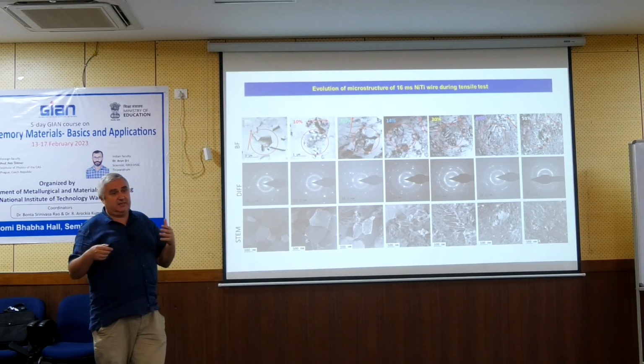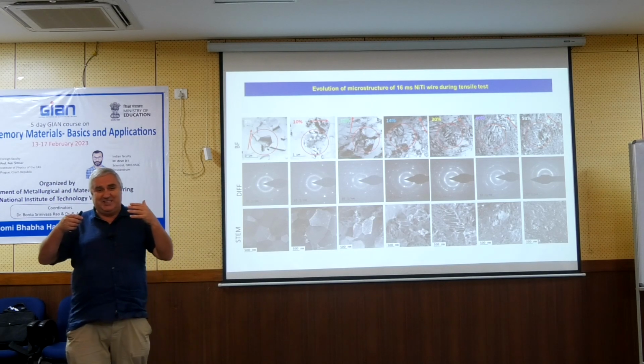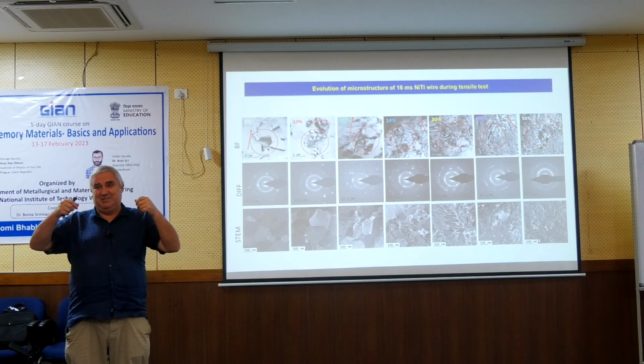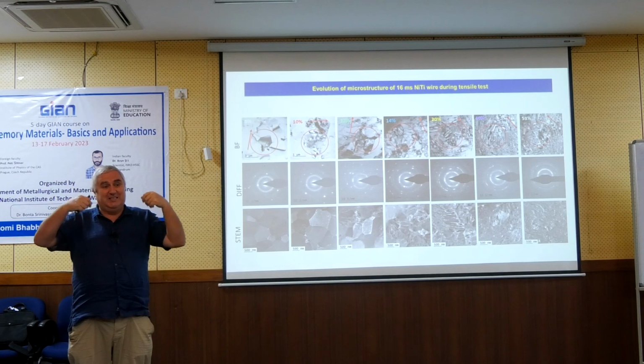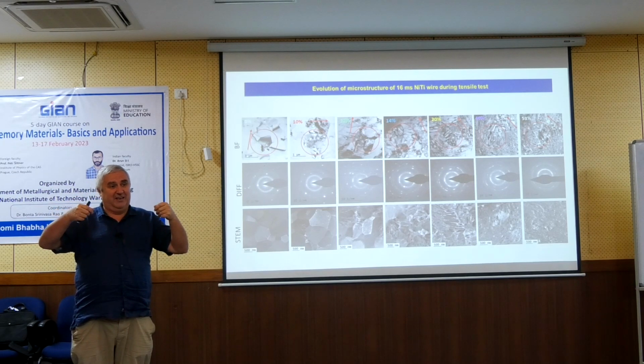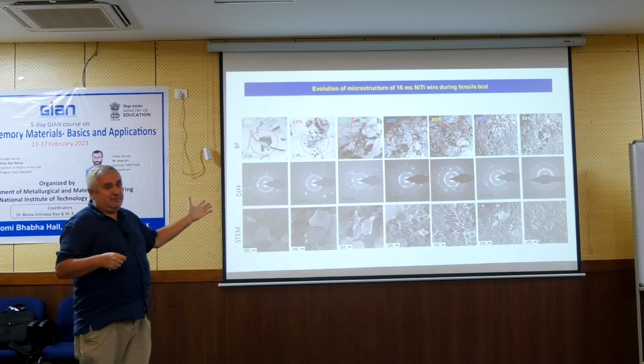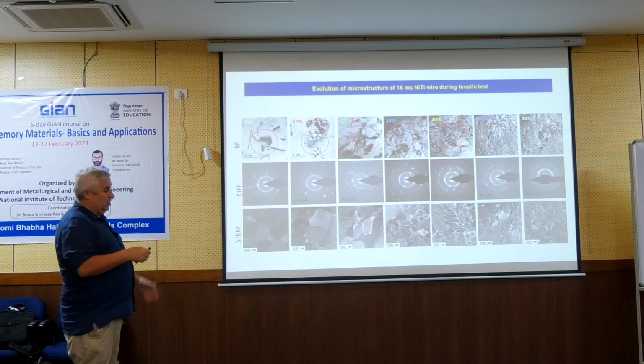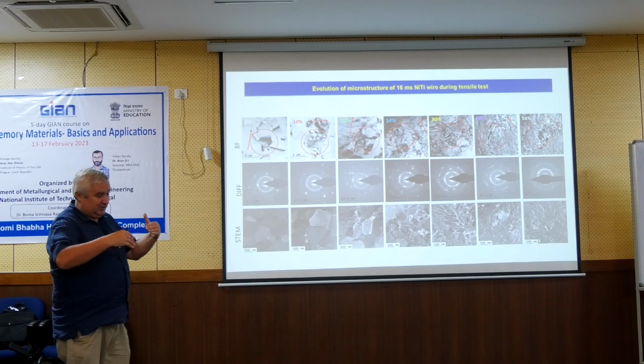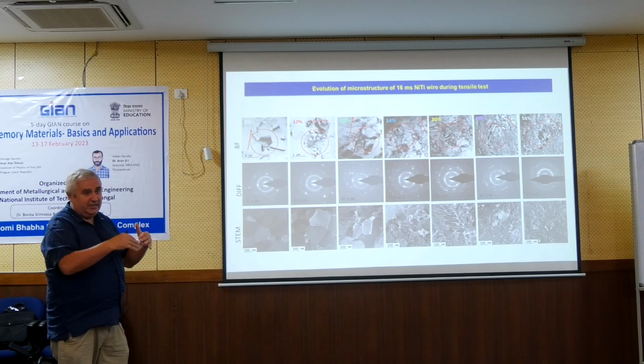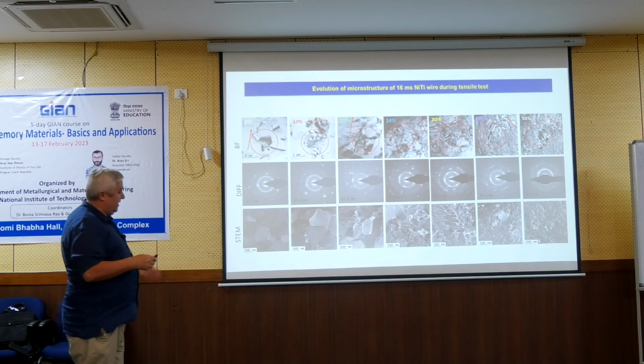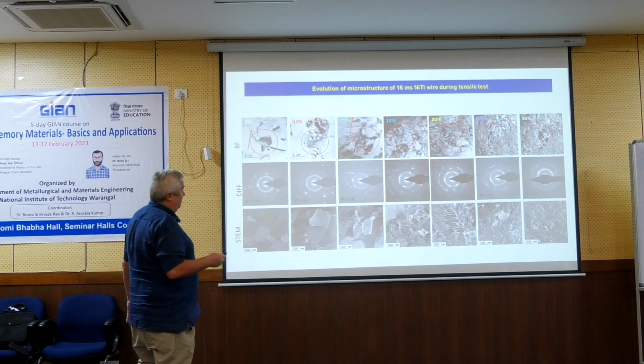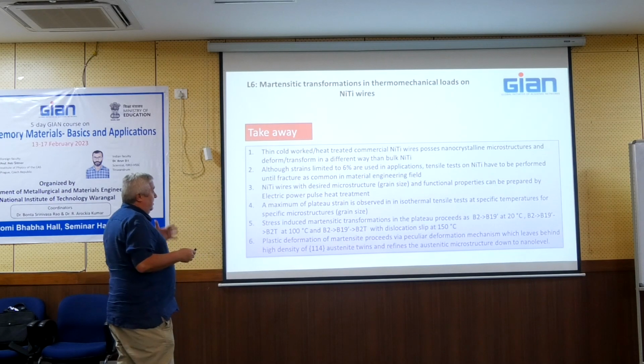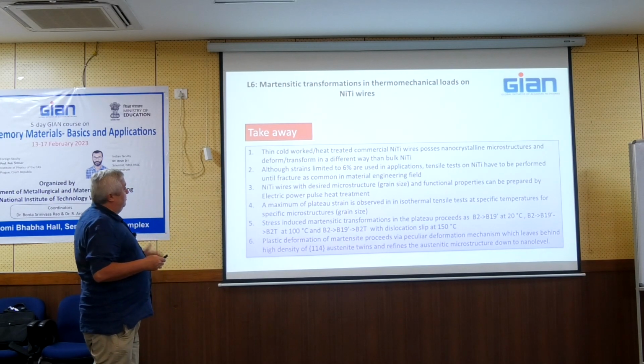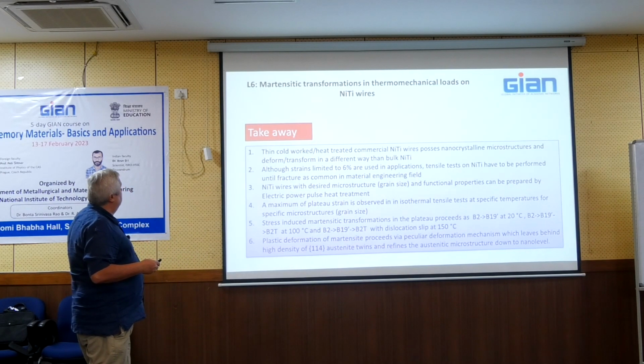And so you may ask, what are the microstructures in the wire when it deforms? Because when it deforms, it is in martensite. It is not in austenite. But these experiments cannot answer it. Here we look only at the microstructure which remains after unloading and heating. So we have the evidence. This is some kind of relics of the process, but we don't really know what was there before.